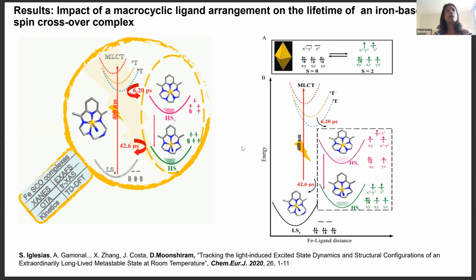So while impressive developments have been conducted on complexes that go from a singlet to a quintet state, most of them have lifetimes on the order of nano- to a few microsecond time scale at room temperature. In this case, we were able to trap a quintet state that had a very long lifetime of around 42.6 picoseconds at room temperature. And the extraordinarily long-lived quintet state was due to its macrocyclic nature, which could stabilize a hepta-coordinated, so a 7-coordinated, quintet state, and help decrease its reactivity and decay back to the ground state.